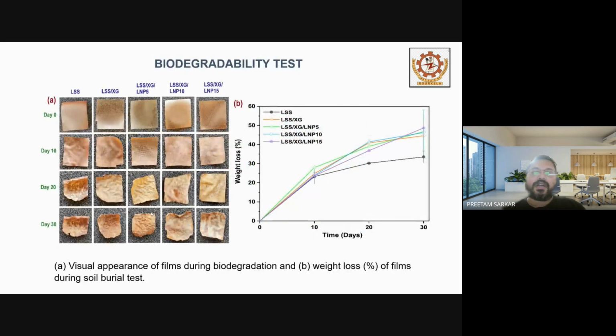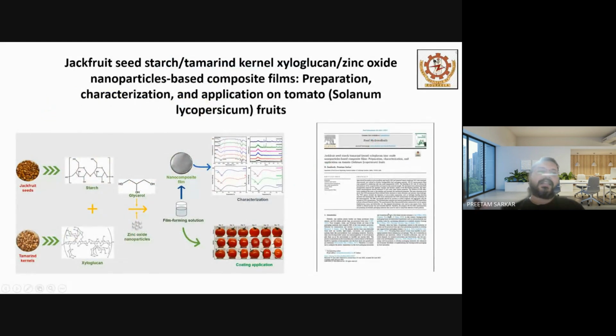That's the first work, and we also did the biodegradation studies. We did it for 30 days, from day 0, day 10, day 20, day 30. We took soil samples and embedded our films inside the soil, and then we can see how they biodegrade, and we characterize the weight loss versus time.